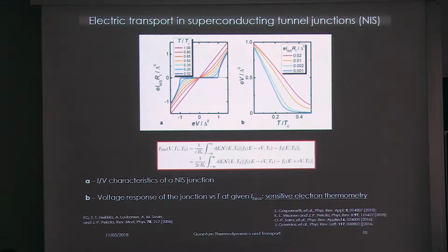You see that, for instance, for large current bias across the junction, there is an important response at higher temperature, whereas if we reduce the current across the system, we have a very sensitive response at the lowest temperatures. So in some sense, this thermometer is nice because according to the current that we put in, we can decide the range of operation where it is more sensitive or less sensitive. And then, of course, what is important is that the thermometer has to be operated in a suitable way so that it does not overheat the system too much, because we want to perturb the system in the smallest possible way, in order not to alter the rest of the physics that we wish to investigate.